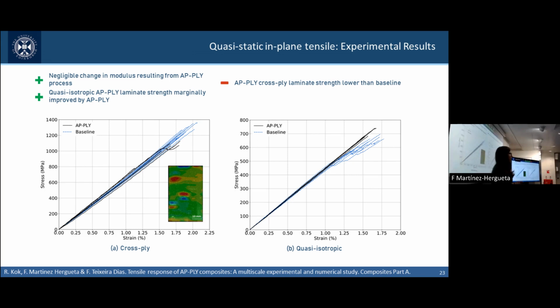And these are the first results that we obtained experimentally, which is the comparison between the baseline angle-ply laminates and this AP-PLY response. The first finding is that there is no impact on stiffness, doesn't matter which configuration you try. The cross-ply and the quasi-isotropic laminates present the same stiffness as the conventional composite.